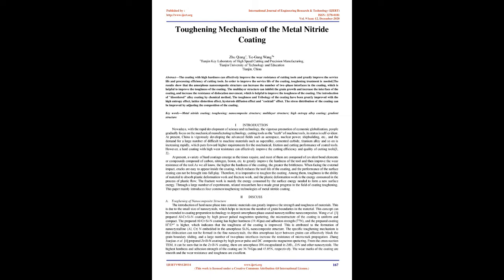The introduction of hard nanophase into ceramic materials can greatly improve the strength and toughness of materials. This is due to the small size of nanocrystals, which helps to increase the number of grain boundaries in the material. This concept can be extended to coating preparation technology to deposit amorphous phase-coated nanocrystalline nanocomposites. Wang et al. 3 prepared AlCrSiN coatings by high-power pulsed magnetron sputtering. The microstructure of the coating is uniform and compact.